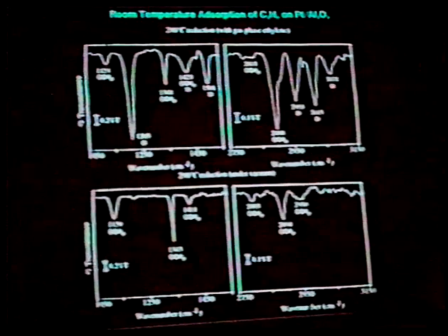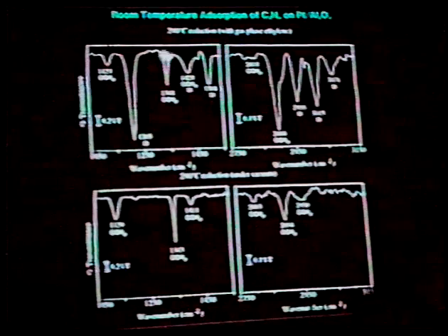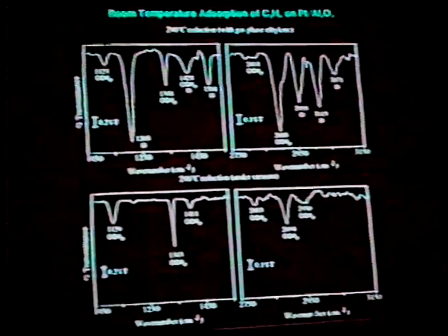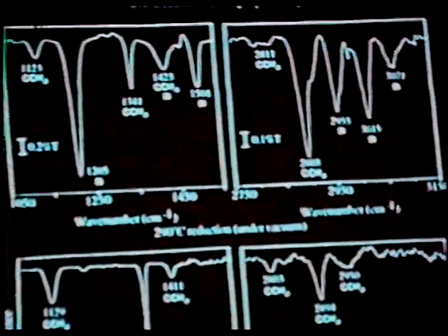Your interpretation of these results, however, changes once you evacuate the cell to remove the excess ethylene. This is done at 290 degrees, and what you find is when you remove the excess ethylene in the gas phase, all of your pi bonded peaks just plain disappear. They disappear as fast as you can hope to look at the spectrum.